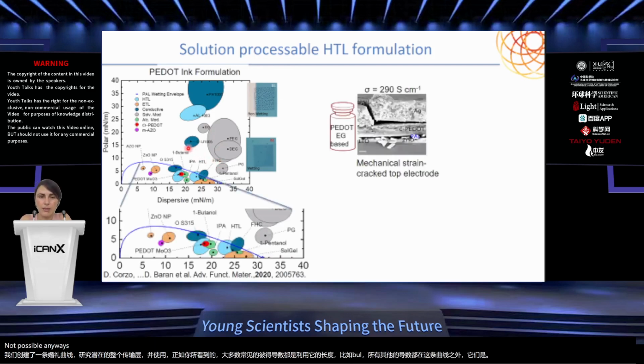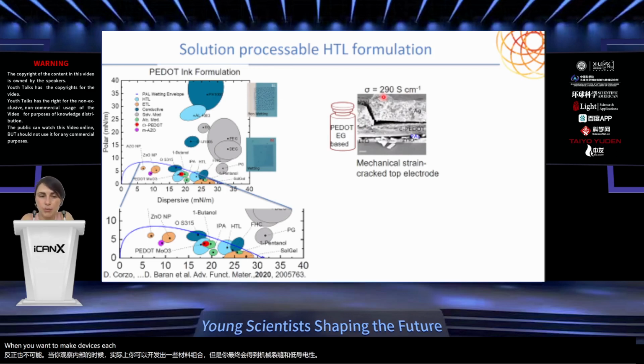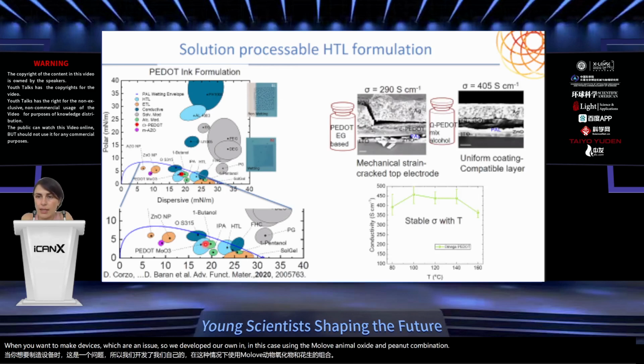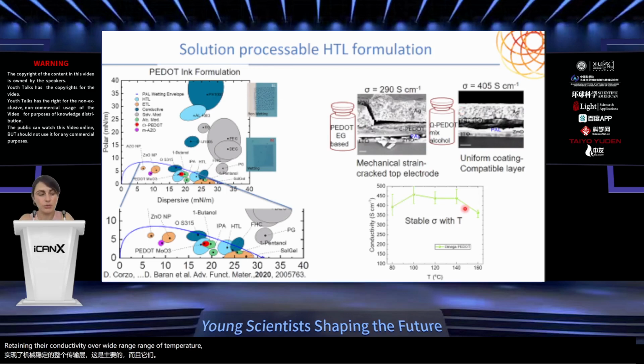So to understand this, we have used the PTB7-Th and IEICO-4F system, created a wetting curve and looked into potential whole transport layers. And as you see, most of the common PEDOT derivatives that are using ethylene glycol and all other derivatives are outside of this curve, which are not possible anyway. And when you look to the inside, you can, in fact, develop some of the material combinations. However, you would end up with mechanical cracks and suffer from low conductivity when you want to make devices, which are an issue. So we developed our own ink in this case using the molybdenum oxide and PEDOT combination, and achieved mechanically stable whole transport layers that are printable, and also they were retaining their conductivities over a wide range of temperatures, which was quite important, as I mentioned earlier.